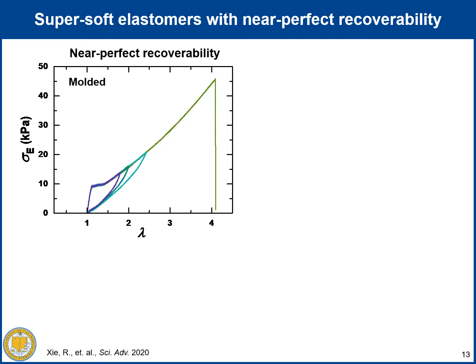In order to examine the mechanical property of a UV cured bottlebrush statistical polymer, we first looked at a molded sample rather than a printed one. When plotting the engineering tensile stress versus extension ratio, the bottlebrush elastomer undergoes a unique yielding transition when the yield stress is surpassed, thus dividing the tensile curve into the pre-yield response and the post-yield response. Additionally, such yielding transition is near perfectly recoverable, as shown after multiple cycles across the yielding.